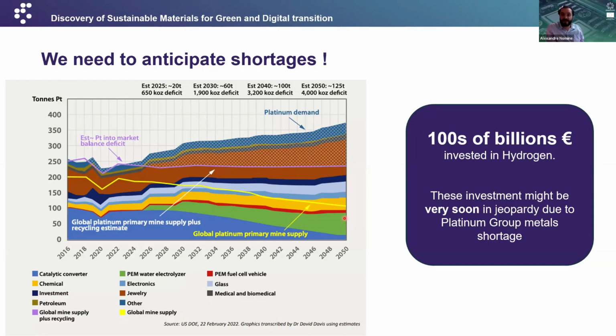Another point in this graph that is extremely important to mention: I told you, we also need iridium. Iridium can be used for hydrogen because it's a platinum group metal. It's quite similar in terms of chemical properties. Here the fact that recycling increases is not good news. It's terribly bad news, because we have iridium only because we extract platinum. But once we have extracted platinum and removed iridium, when we recycle platinum, there is no new iridium. I mean, no iridium has been created by, I don't know, some nuclear reaction inside of the platinum.